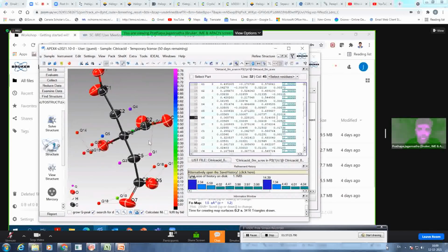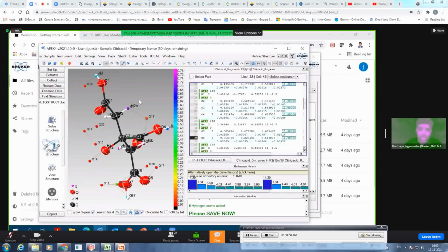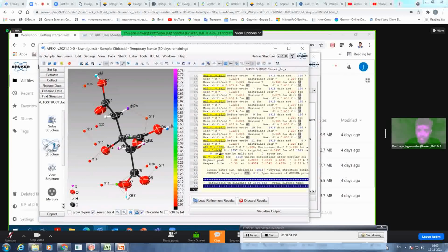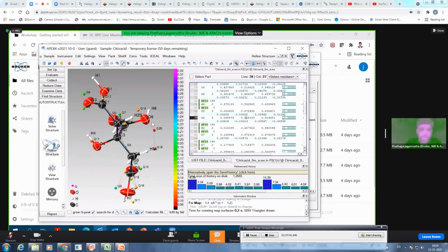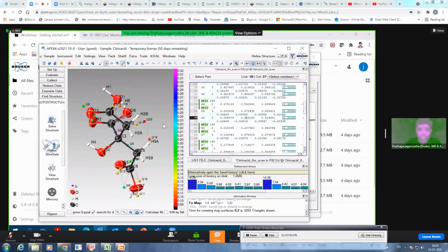Then you can do anisotropic refinement down to 7% with 0.78 as the highest residual density. That is because of your hydrogen, which still has to be added. An easier thing is ShelXL automatic HFIX you can do. You have fixed the hydrogen. You can do the refinement again. You are down to 4.4 with almost nothing left in the electron density.